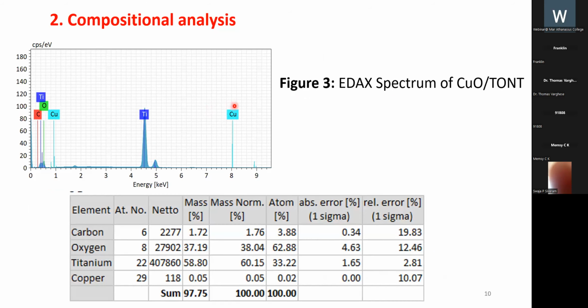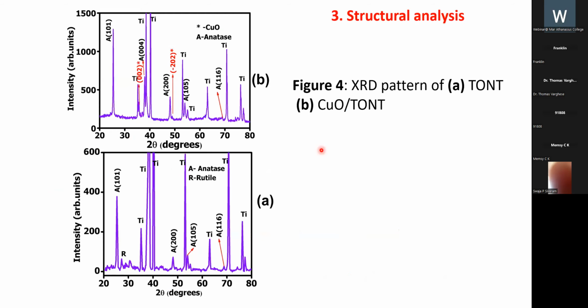Figure 3 shows the EDAX spectrum, and it contains Ti, oxygen, and a small percentage of copper incorporated in the sample. Figure 4 shows the XRD pattern of TONT and CuO/TONT. The peaks around 25.3 degrees, 48.1 degrees, 53.9 degrees, and 68.7 degrees correspond respectively to the 101, 200, 105, and 116 crystal planes of anodized TiO2.